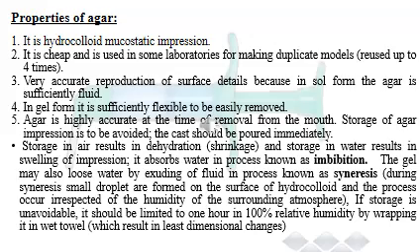During syneresis, small droplets are formed on the surface of the hydrocolloid, and the process occurs irrespective of the humidity of the surrounding atmosphere. If storage is unavoidable, it should be limited to 1 hour in 100% relative humidity by wrapping it in wet towels, which results in the least dimensional change.